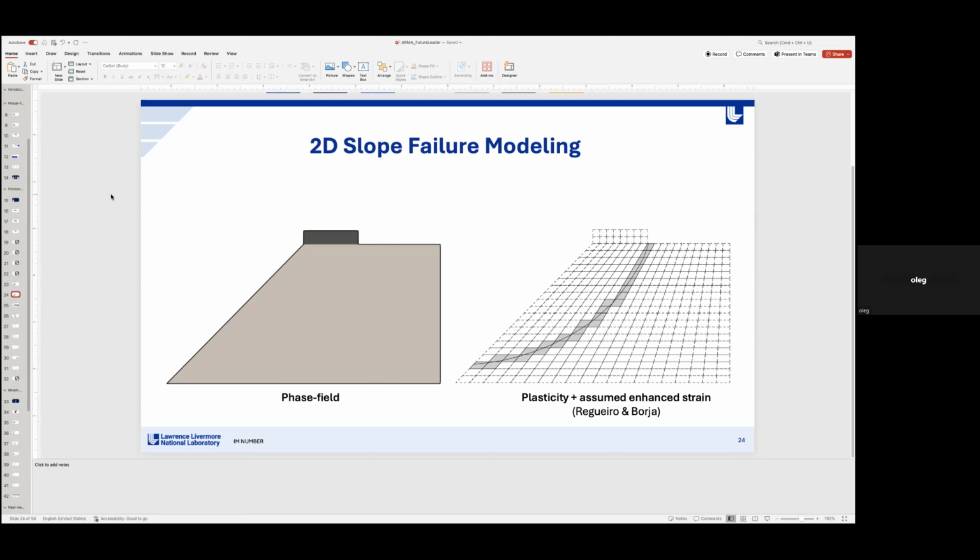So basically, if you introduce, let's say, a planar fracture using the phase field method, then it's like a non-compliant fracture. So it does not affect normal compliance. If you send an elastic wave normal to the fracture, it will go through, right? It will not bounce back.